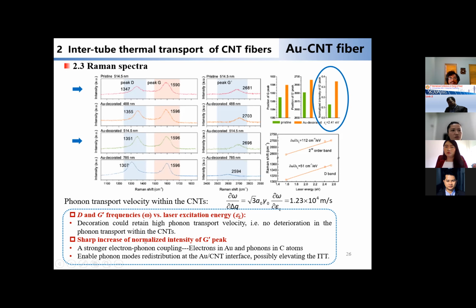Furthermore, let's look at the sharp increase of the normalized intensity of the G' peak. It reveals a stronger electron-phonon coupling, that is, electrons in gold and phonons in carbon atoms, and enables phonon mode coupling at the interface, possibly elevating the interface transport.